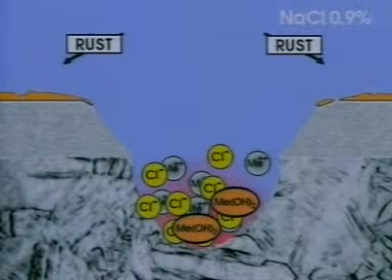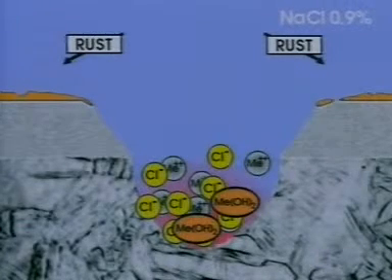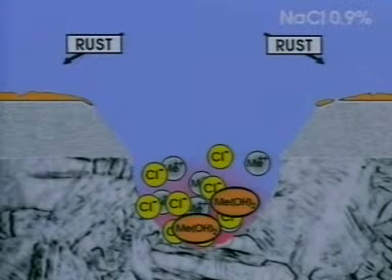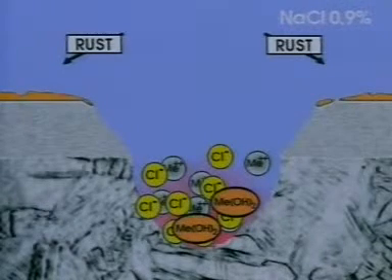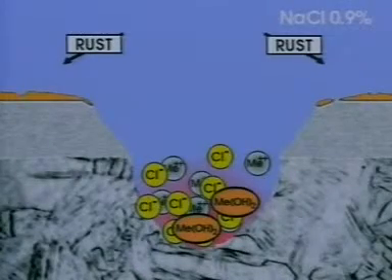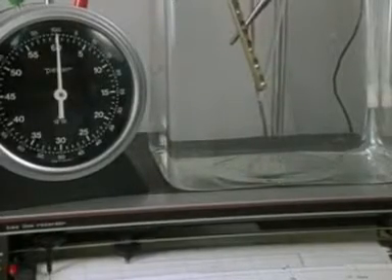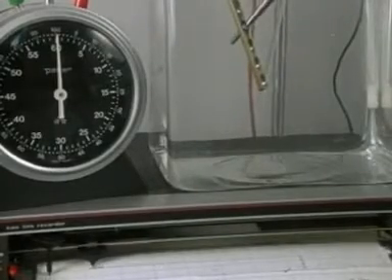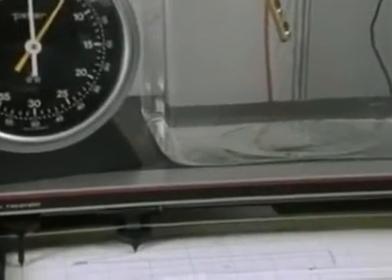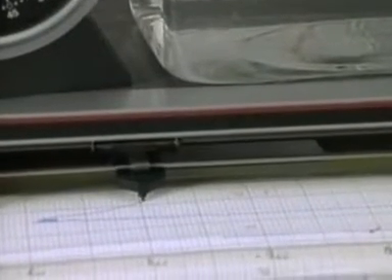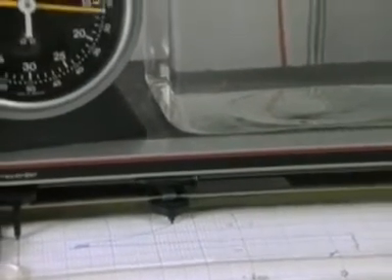Growing pits lose some of the concentrated metal chloride molecules to the surroundings. As they diffuse away, the solution becomes less acidic and the solubility of the metal falls and precipitates as an oxyhydroxide a small distance from the mouth of the pit. This laboratory experiment demonstrates destruction of the passive layer as occurs during pitting corrosion. The plot indicates the reconstruction of the passive layer until full repassivation.